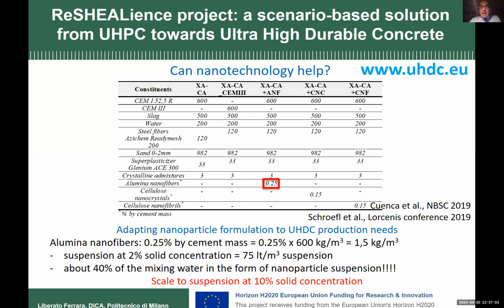So with the companies, we developed a process to produce a 10% solid concentration suspension. The key was not only making a denser suspension, but dispersing the fibers adequately within that suspension. We were able to successfully produce this more concentrated suspension.